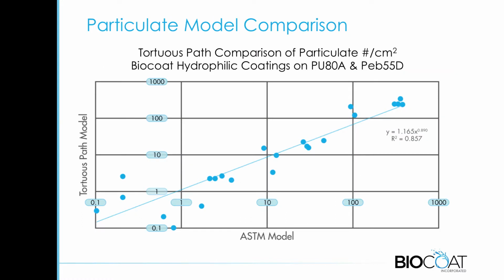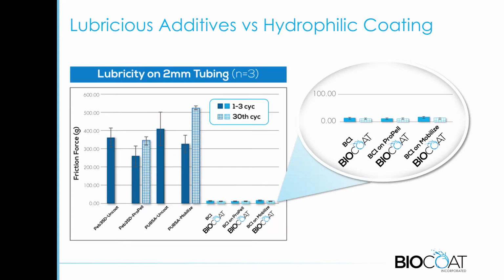So for example, looking at two different models of generating particles, we used this ASTM cardiology model and a serpentine tortuous path. There was a very good correlation between the two when we took coated rods. However, it's not one-to-one. While the ASTM model typically has higher particulate numbers, it gives a nice correlation with the other model. So either one can work, but you can't just interchange between the two. This is an example of how you get similar results, but really need to define the entire test system.